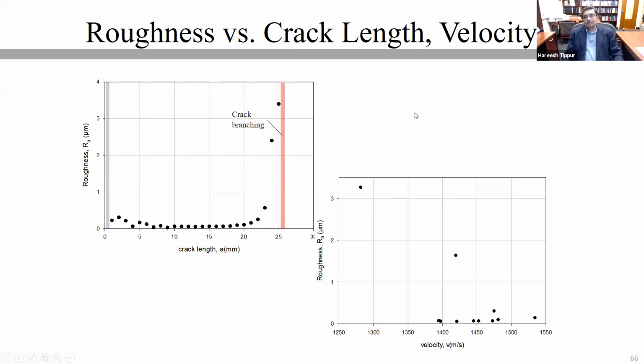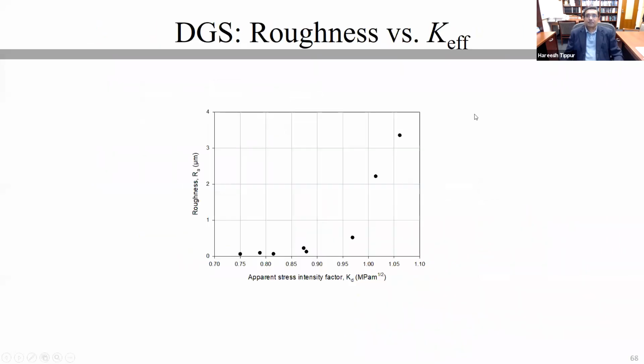We plotted roughness as a function of velocity because this will give you a significant advantage in terms of simply measuring the velocity and making some post-mortem measurements in order to identify what caused the branch. So here, we did not see any obvious trend. So this again departs from the polymer literature, where glass fracture, particularly dynamic fracture, does not correlate with what is reported in polymer literature.